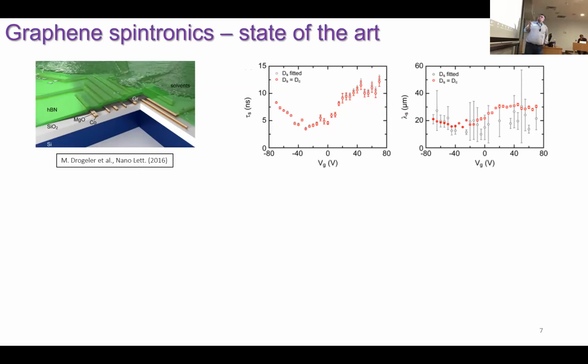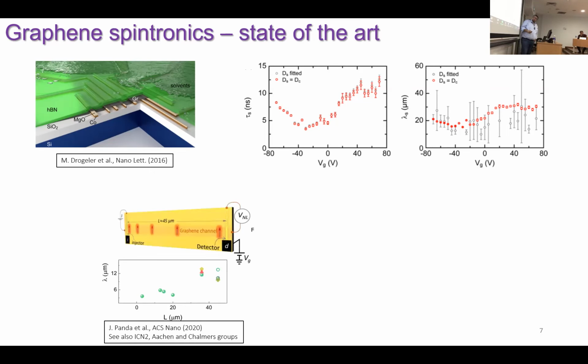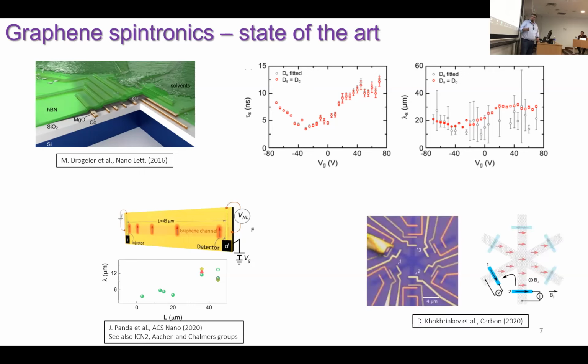And of course, since then, there have been lots of breakthroughs in the field. For example, it was shown 5-6 years ago that you can improve the spin transport properties of these materials up to 10 nanoseconds, or you can transmit the spin information over 30 microns, which is the highest ever measured in any material system. So graphene still works, but it is still orders of magnitude smaller than what the theory expects. It was shown that you can also obtain such long spin relaxation lengths or spin communication in large scale CVD graphene, and you can build some simple spin circuits with this large scale graphene.